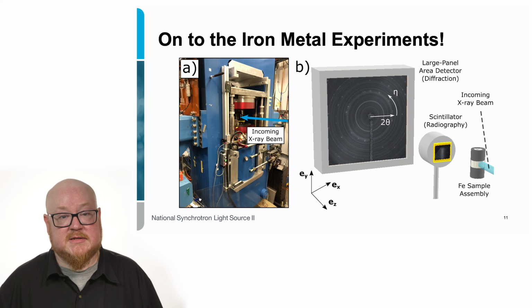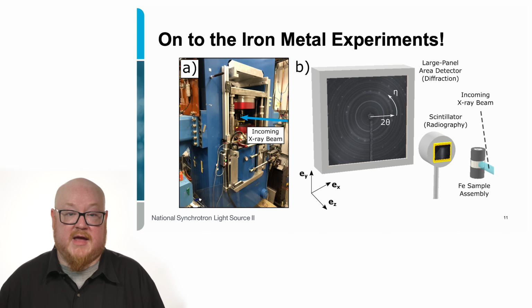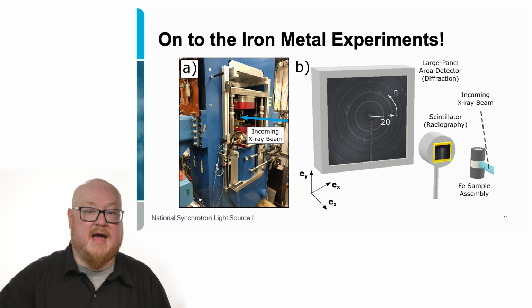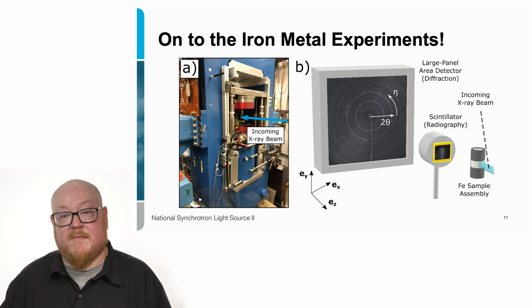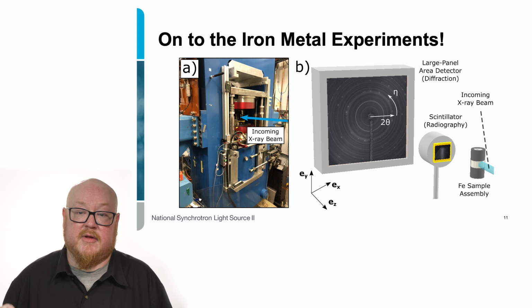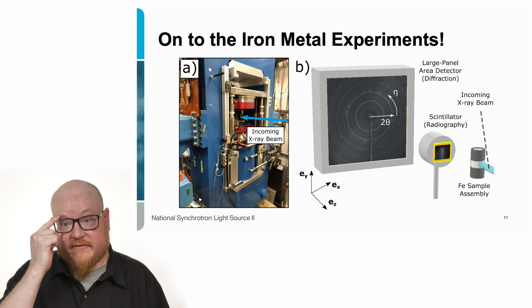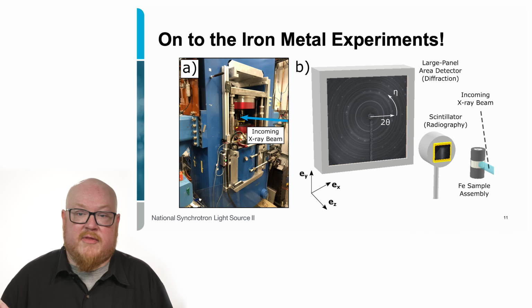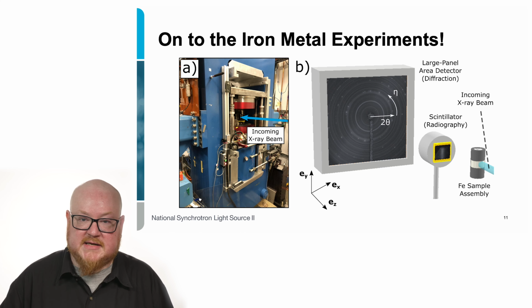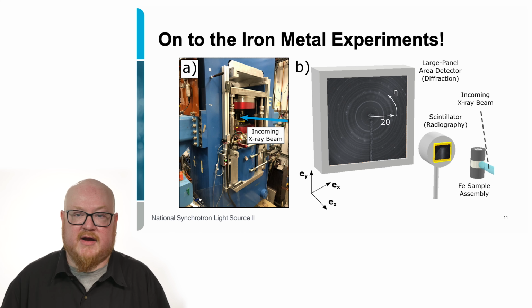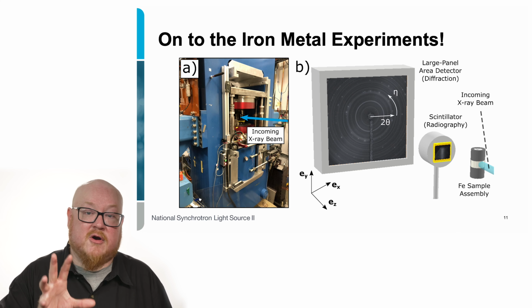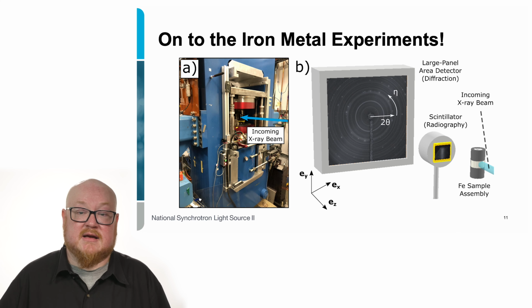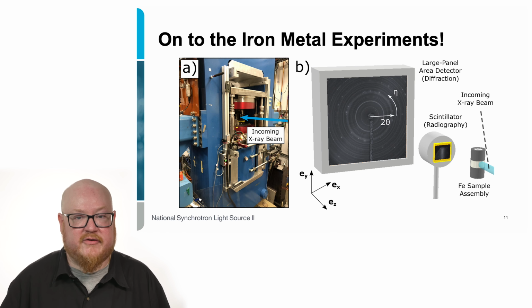So let's talk about these experiments that we did on the iron metal. You can see on the left is a picture of the press, and we have the incoming X-ray beam that shoots right in between the anvils there. All the way on the right, we see a schematic of where the cell assembly is, and your iron sample is right in the middle. The incoming X-ray beam hits your sample, and then we can use what's called a scintillator, which is just a fancy word for a crystal that lights up when the X-rays hit it. And we can use that in order to take images directly of the sample while it's at high pressure and temperature. And then you can see that there's a large panel area detector behind it that allows us to collect the X-ray diffraction data. And we'll talk about all of this in just a moment.